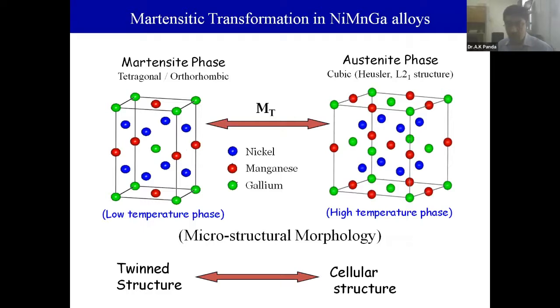Fundamentally, I start off with two structures, basically, the martensitic phase and the austenite phase. Austenite is basically the high temperature phase, and you step down into a low temperature phase. It is mostly martensite, which can be either tetragonal or rhombic. There are many other combinations of the tetragonality, primarily based on monoclinic systems and 5M, 7M that I'm going to discuss later. Basically, when you go down from a high temperature to low temperature, there is a twin structure, and due to the twin structure you have a generation of martensite phase. It starts with nano twinning, and you land up getting a martensite structure.